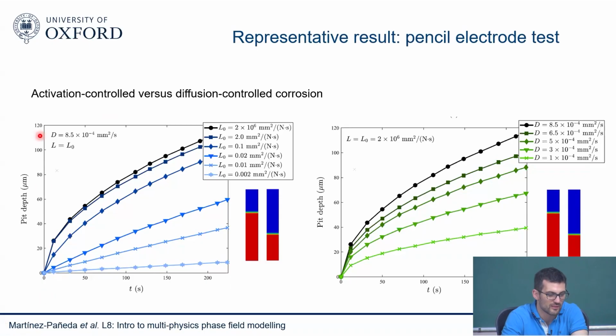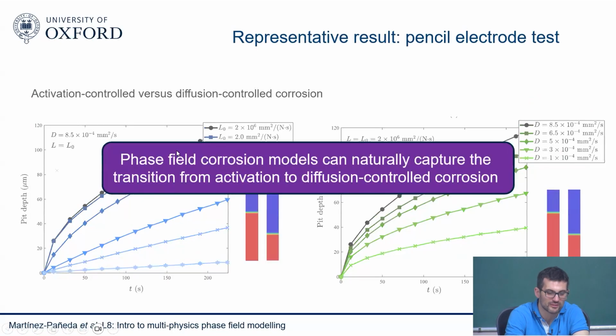So you can see here, this is the pit depth versus time. This linear behavior is typical of activation control corrosion. But as I ramp up my corrosion current density by ramping up my mobility coefficient, you can see that you get into this parabolic behavior that is typical of diffusion control corrosion. And when you are in the diffusion control corrosion regime, you can see that the parameter that matters, what changes the predictions, will be a change in the diffusivity. This is the idea. So yeah, an important key takeaway: these phase field corrosion models, by solving these kinds of Allen-Cahn and Cahn-Hilliard equations, can naturally capture the transition from activation to diffusion control corrosion. This is an important takeaway.